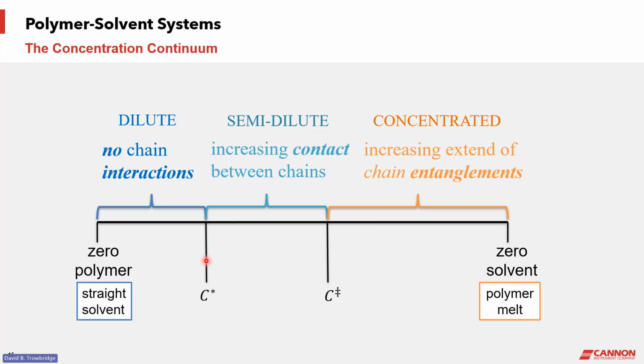So this is called the critical concentration, or sometimes the overlap concentration, because that's what's happening to the polymer molecules. If they get the concentration high enough, they start to interact with one another. But in the dilute region, there are no chain interactions. And then we begin to see interactions, and at another transition, another critical concentration, we start to see a persistence in the contacts between the polymer molecules that allow them to entangle, and we get even a different behavior in the concentrated regime here.